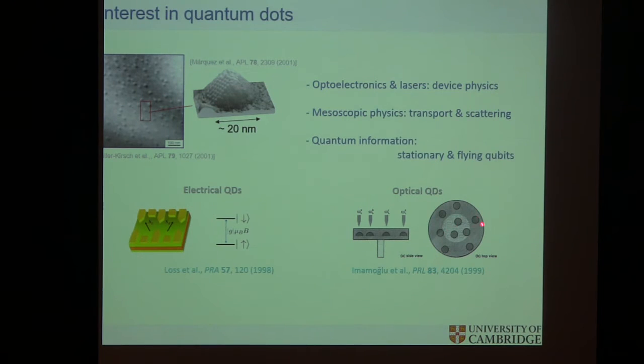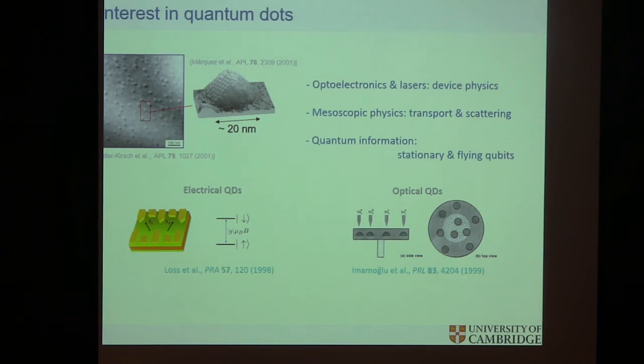The idea is you have all these randomly located quantum dots in a microdisk. The quantum dots each have a single spin, and they're at random wavelengths, because they emit at different wavelengths, there's a big dispersion, and they're in this cavity defined by the whispering gallery mode of this microdisk. Fantastic. So all you have to do is take this one, and that one, for example, that normally wouldn't talk to each other, because they're too far, it's about 3-4 microns, and bring them in resonance with the cavity mode, and then they talk through the cavity. They exchange energy, effectively, through the cavity mode, and then you have that coupling, that interaction that we're talking about.